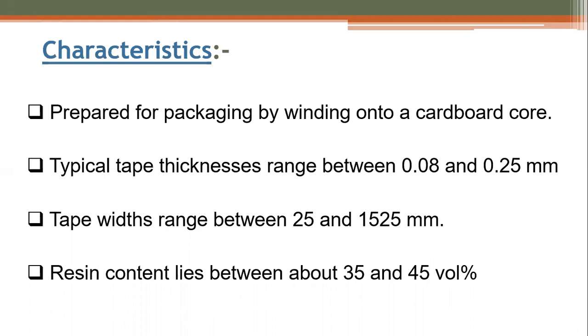Next, typical tape thickness ranges between 0.08 and 0.25 mm. So it is a very thin material, less than 1 mm. 0.25 mm is a quarter of 1 mm. So it is very small. The thickness of the tape produced for the prepreg is very low, less than 1 mm only.